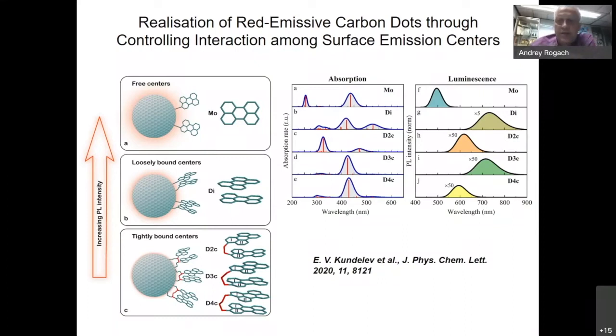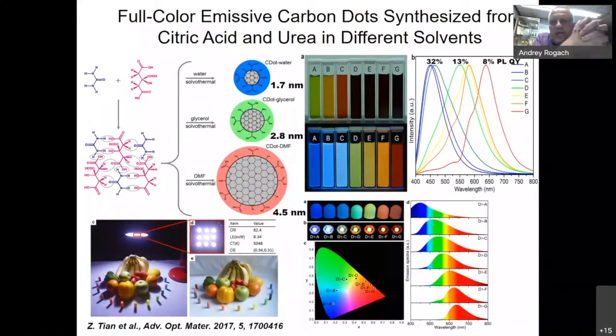This kind of modeling is somehow complementary, but actually it's the next step to what was done before by my Czech colleagues, because here we can predict luminescence spectra of these materials as well. And here this was done in practice now. So coming away from purely theoretical calculations, what we did here, we made full color emissive carbon dots by taking these two particular precursors, citric acid and urea, and we achieved different size of these luminescent domains inside carbon dots because we ran those syntheses in different solvents.